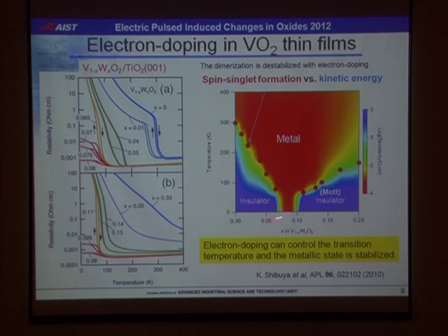Actually, the valence state changes from 4+ to 3+. So, for example, at 0.33, all vanadium becomes 3+. In this area, it's a Mott insulator, as is well known in V2O3. Anyway, the ground state is an antiferromagnetic insulator. So the point is that electron doping can control the transition temperature, and the metallic state can be stabilized by chemical substitution.